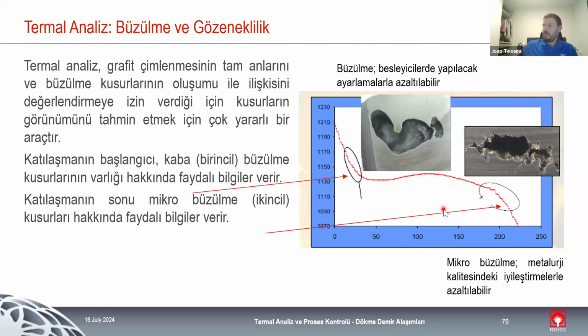And in here is just to illustrate at what points in the thermal analysis we have macro shrinkage and micro shrinkage. So all the macro shrinkage happens early on during solidification, and normally this has nothing to do with the metallurgic status of the bath. It's normally only because of incorrect position of sleeves, of feeders, or not enough feeders. So it's not a metallurgic problem, it's a design problem of the gating system and the feeder position.